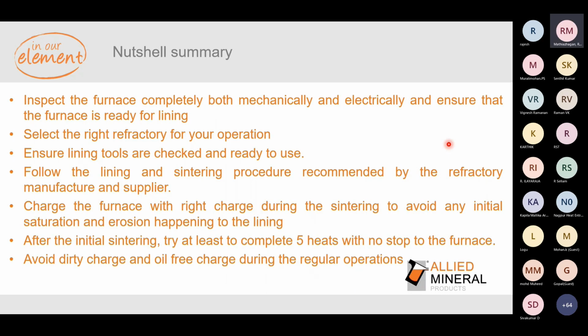So in a nutshell, I suggest for a better refractory lining life in your furnaces, inspect the furnace completely, both mechanically and electrically, and ensure the furnace is ready for lining. Select the right refractory for your operation, depending upon what you melt. Normally for iron melting operations, nothing much. Normally it is only silica because that is a cost-effective solution. But the boron oxide percentage can be varied from 0.6 to 1%, depending upon your operation.